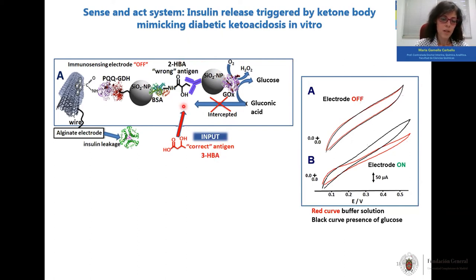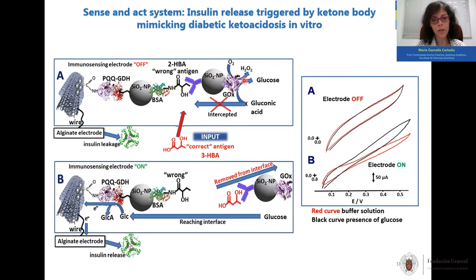Both are similar in structure, and this antibody is specific for 3-hydroxybutyric acid, but still, due to their similarity, it's going to recognize 2-hydroxybutyric acid, but in a weaker way. Therefore, when we add this input, the 3-hydroxybutyric acid, a competition is established between these two antigens, and therefore the conjugate gets removed from the surface of the electrode. Now glucose can reach the surface of the electrode, producing the oxidation of glucose and with the subsequent movement of electrons that is translated into the controlled insulin release.